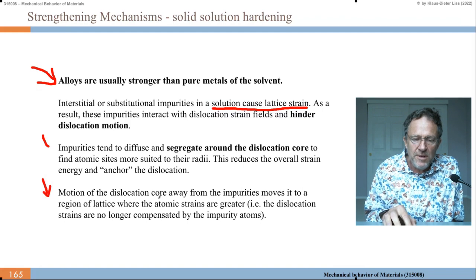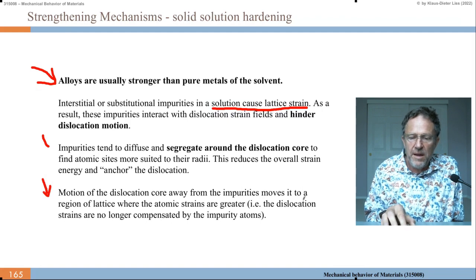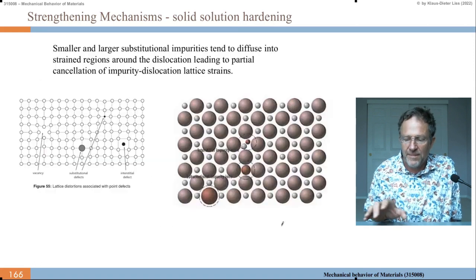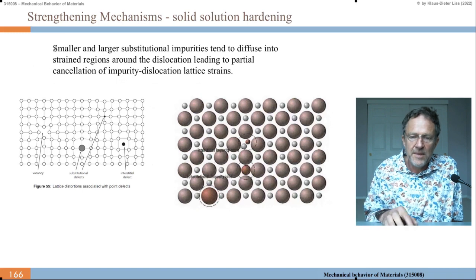So motion of the dislocation core away from the impurities moves it to a region of lattice where the atomic strains are greater, i.e. the dislocation strains are no longer compensated by the impurity atoms. So here, smaller and larger substitutional impurities tend to diffuse into strained regions around the dislocation, leading to partial cancellation of impurity dislocation lattice strains.